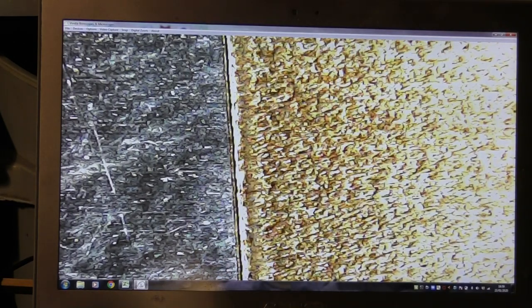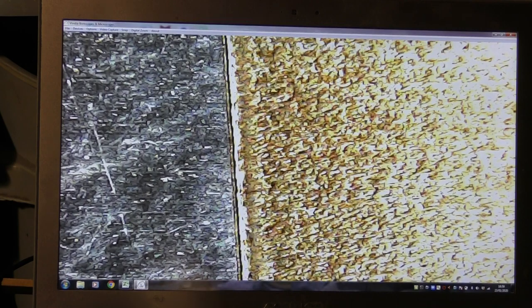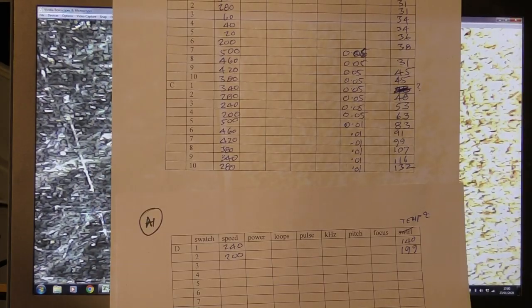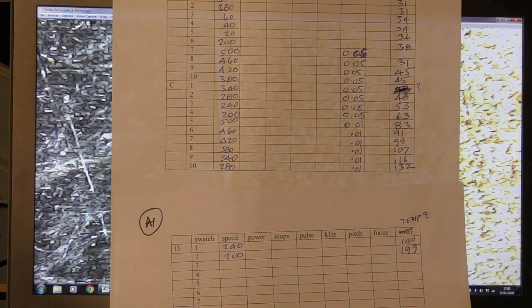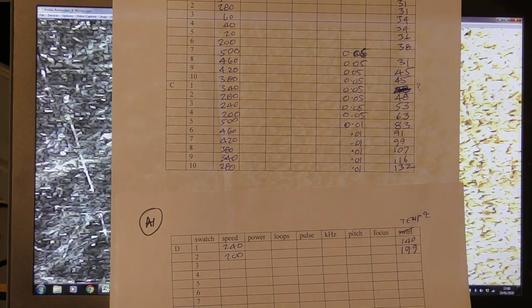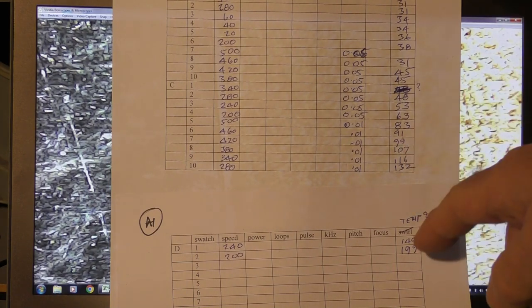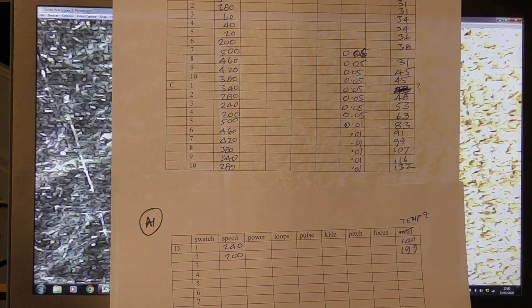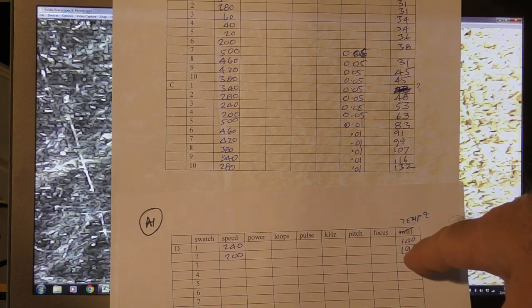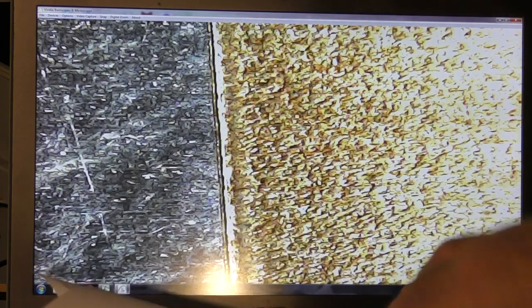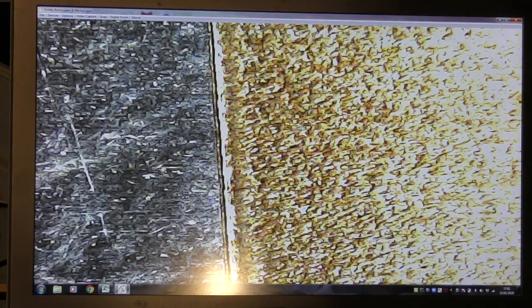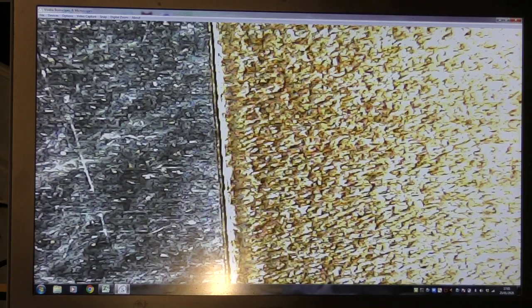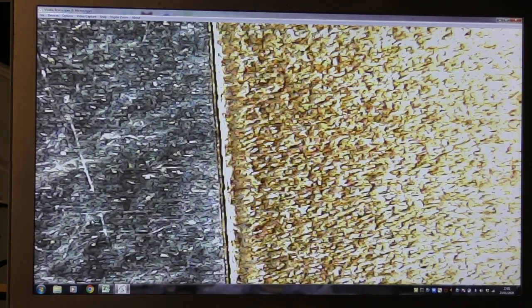So that's 10 microns spacing and all of a sudden we've lost the center of the lines because I suspect that what we're doing there is we're melting the surface and it's just flowing together. For the steel to melt it's got to be up to something like about 1400 degrees C, and we've got to burn through the oxide layer to start with which has got a melting point of about 3000 degrees C. Now we're not seeing anywhere near those sorts of temperatures projecting through to the back of a half mil sheet of material, but we are getting up quite high at 199 degrees C when we do something like this.